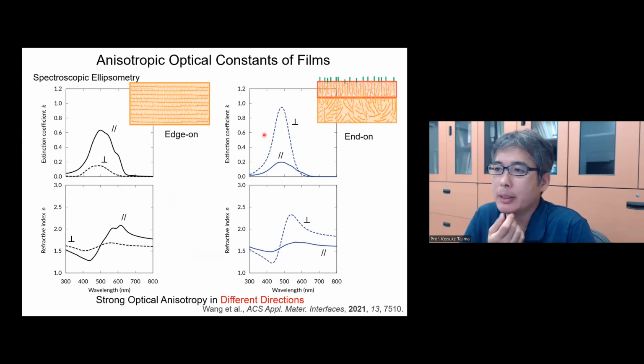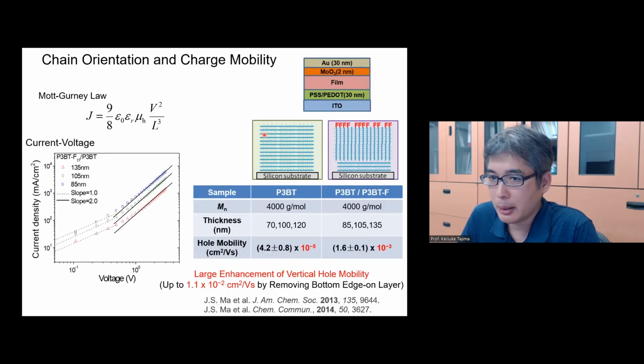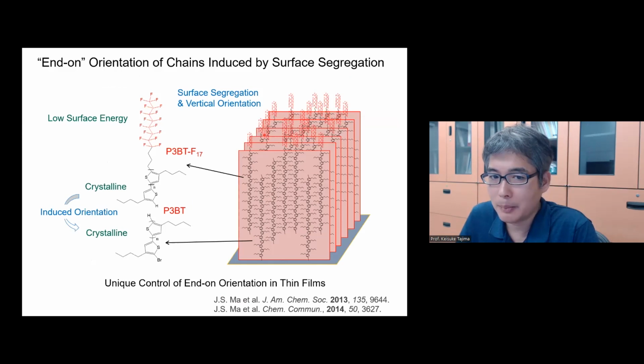Okay. The length of the alkyl chain changes the crystallinity of the polymers a lot. So we know that particularly in this poly(3-alkylthiophene) case, a shorter alkyl chain gives a very high crystalline material. With a longer chain, you get less crystalline. So it affects the crystallinity of the material. And we did some investigation on this issue, like what happens if you change the alkyl chain length, or even change the length of the surface alkyl chain in the surface monolayer and the length in the bulk. What's going to happen? But we don't have a clear tendency.